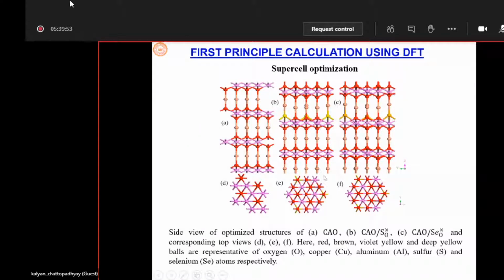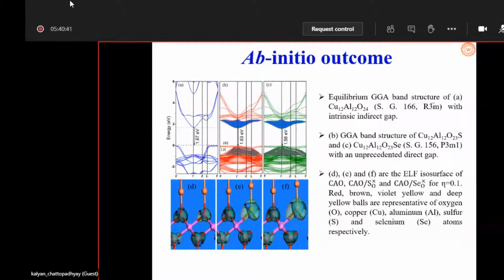So this is done, and when we optimize the structure, we could get some interesting results. Basically, the most important thing is that the local symmetry gets changed. It is obvious because as we replace the oxygen by sulfur or selenium, the bond angle gets changed and the local symmetry gets changed. So it must have some effect on the band structure, because symmetry and band structure are intimately related. Actually, we found that the space group changes from R3 bar M to P3M1. That means polytype formation actually took place, and this is the effect on the band structure when these chalcogens were incorporated at the anionic site.